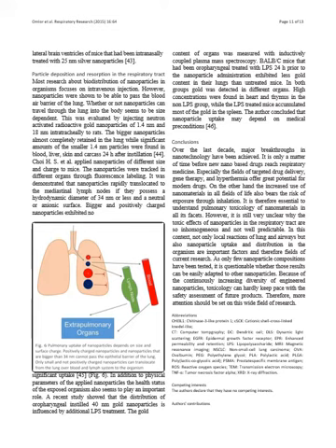This was evaluated by injecting neutron-activated radioactive gold nanoparticles of 1.4 nanometer to 18 nanometer intratracheally to rats. The bigger nanoparticles were almost completely retained in the lung, while significant amounts of the smaller 1.4 nanometer particles were found in blood, liver, skin, and carcass 24 hours after instillation.